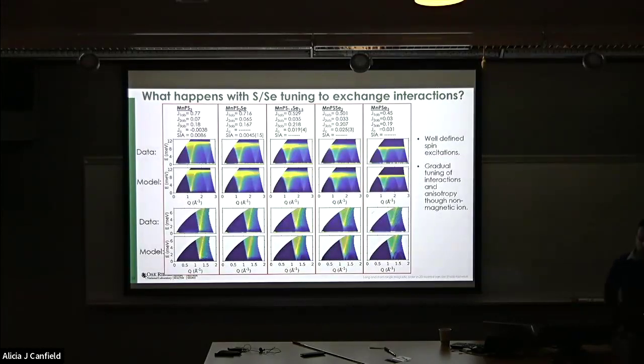So looking at the whole series, we're able to model the data. The data is shown here. The model is down here for the whole dispersion, and just looking at the low energy part, you can see you have this very nice gradual change of the excitations. The top of the band drops down. The low energy part has this very small gap, where you need to put in a little bit of anisotropy, which decreases. And then as you go to the 1.5 case, you start to see the interlayer interactions developing, and you can model these nicely as they increase through the series.